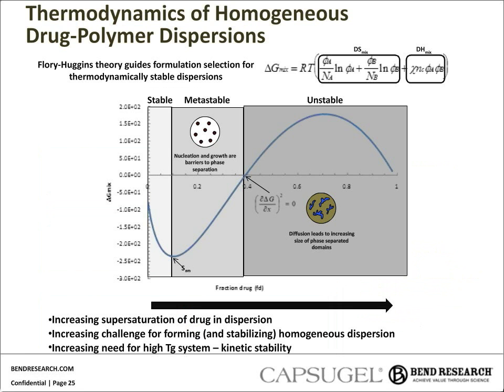If we take a very simplistic view of what I attempted to describe on the previous slide, here we're looking at some Flory-Huggins theory, and we're looking at the free energy of mixing as a function of drug loading into the polymer. From freshman chemistry, remember that if the free energy is negative for a system, then it spontaneously occurs. So everywhere the line is below zero, the material is effectively soluble. But as we swing up the slope in the metastable regime, it's not necessarily a two-phase system, but because we've pre-mixed it, that material is going to stay in solution. However, if we give it mobility, it will relax and phase separate out. That's an important thing to note.